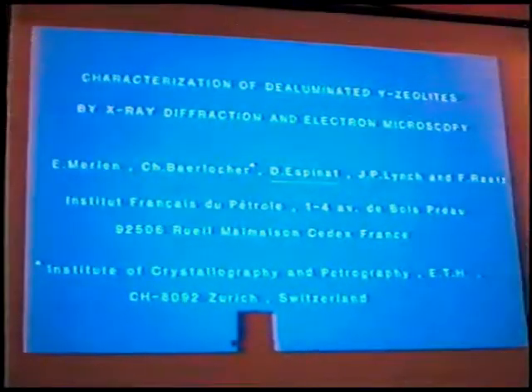The use of Y-zeolite in petroleum industry is of great importance for various refining processes, such as catalytic cracking or hydrocracking. Why can't zeolite be used in its synthetic form? Because, first of all, it lacks stability — the crystallographic structure disappears at high temperature. Secondly, its acidity is unsuitable for the kind of chemical reaction involved during catalytic treatment.